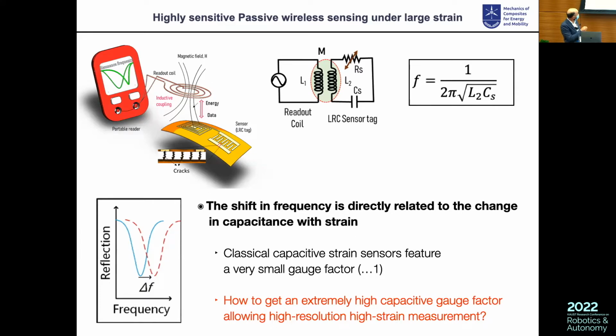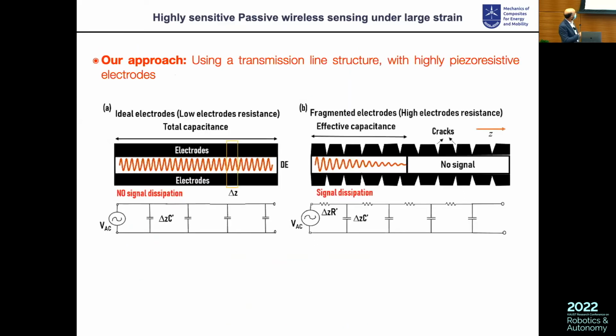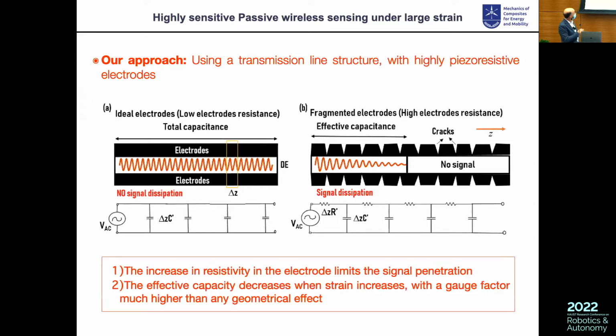So the question comes to how do you design patches like this, in which you have a capacitive sensor with a high capacitive gauge factor. That means a high change in capacity when you have a strain, so you can measure something that is relevant. For this, our approach is to use a transmission line approach. So that means that we are taking a capacitor. This is your capacitive part, with two conductive electrodes, and in the middle you have the dielectric. And what we do is that we make these electrodes very piezo-resistive. That means the resistance of the electrodes can vary a lot with the strain. And this is what makes the thing work.